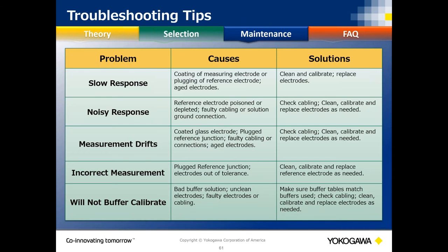I put this in here for you guys to reference later. If you see these problems, these are possible causes, and it goes across everybody. The biggest one that I want you to look at is that noisy response. When you get on your analyzer, there should be a pin for your reference and a solution ground. You can jumper those together, and if your analyzer is bouncing up and down, and you jumper those two in your terminal together, and your measurement locks on, it's a good indication that you don't have good grounding. That's the most common thing that we see, that we have people quick reference test for all the time.